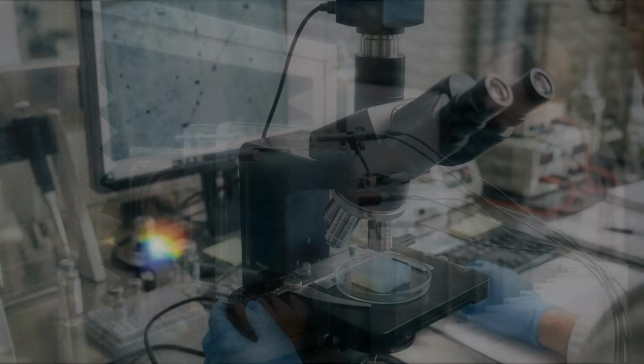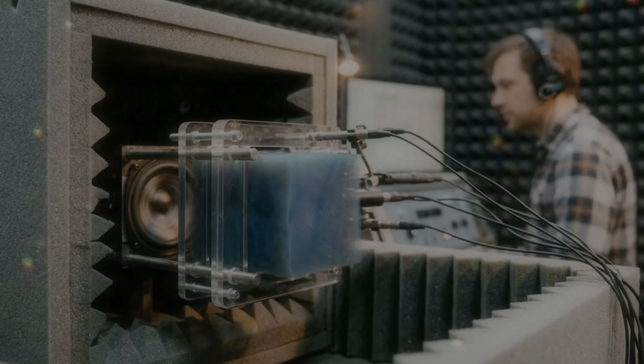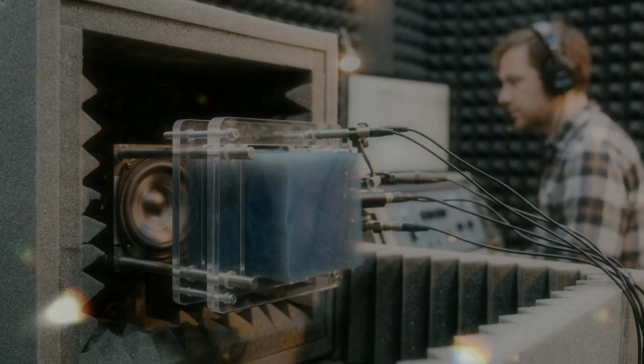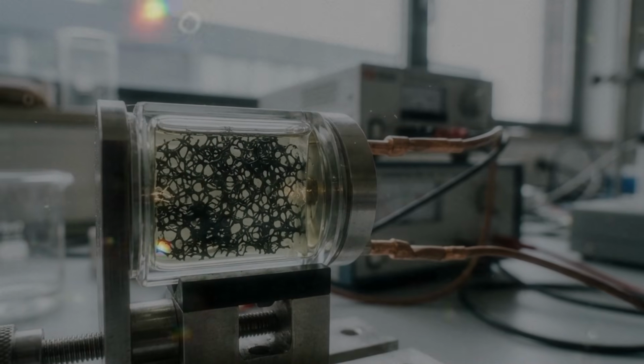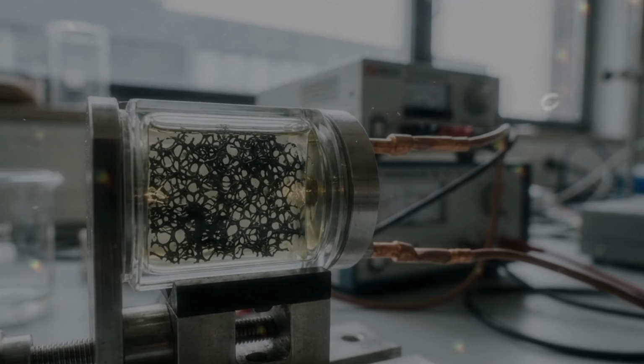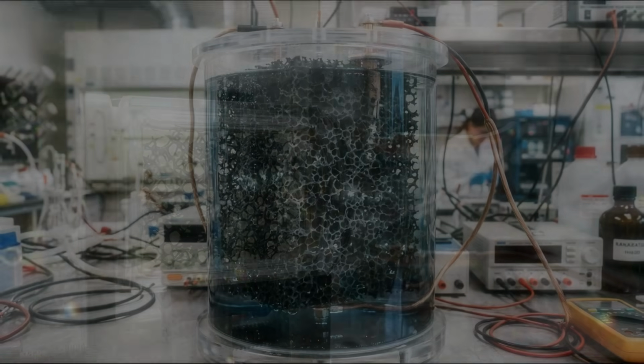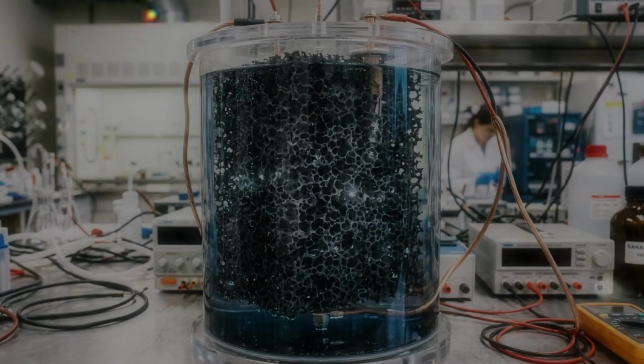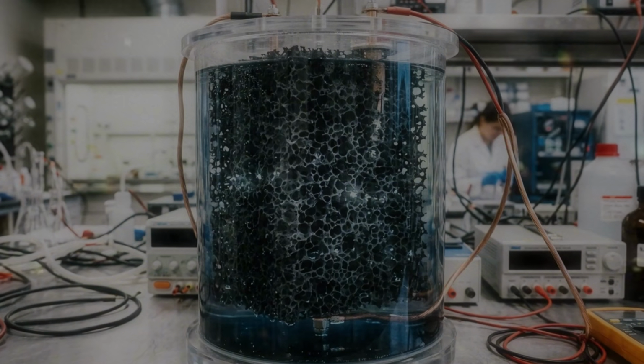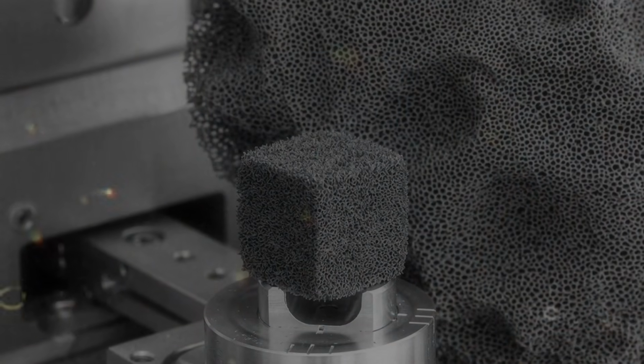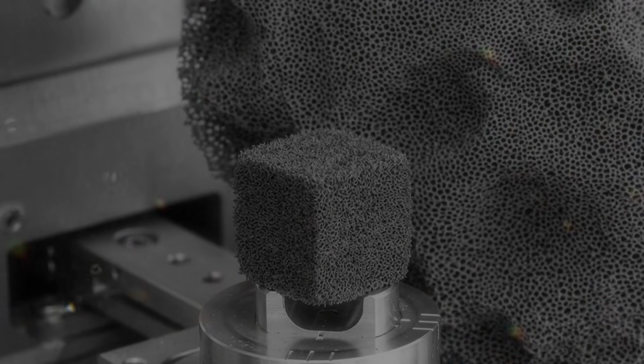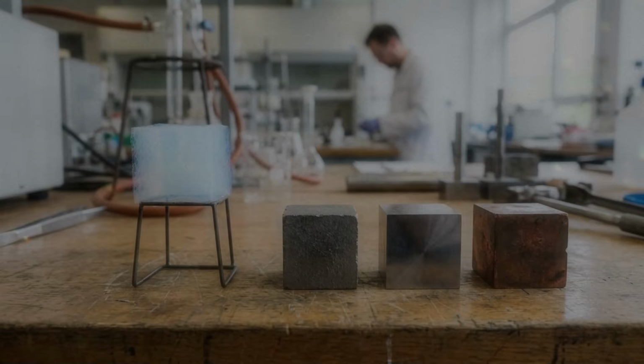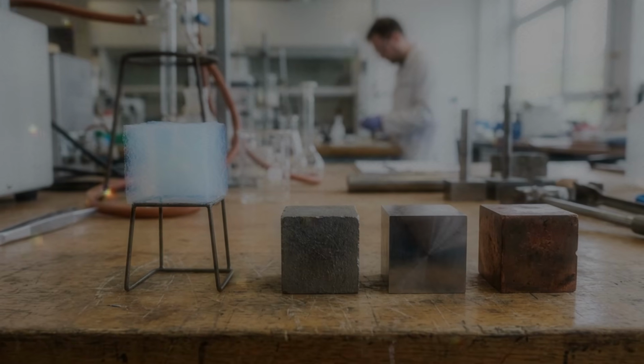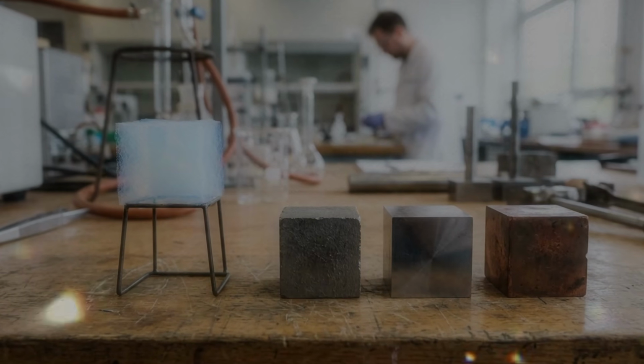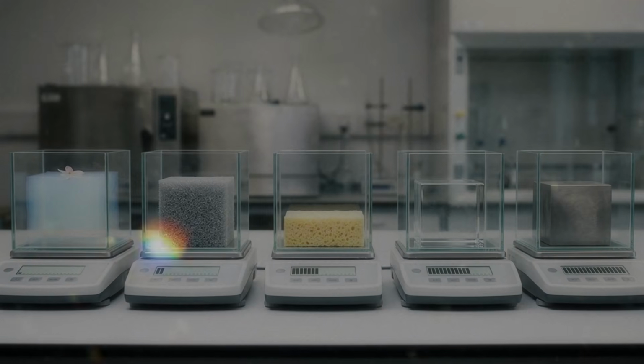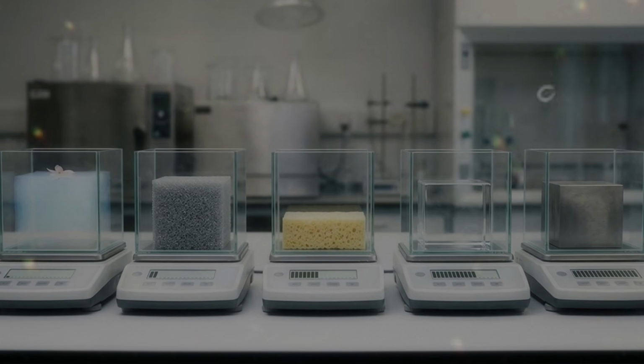A successful process does not need to preserve every pore perfectly. It needs to preserve enough of the structure to meet the intended use. Insulation for a wall may tolerate more shrinkage than a transparent optical panel. An oil absorbent may work well with large irregular pores. An electrode may benefit from a combination of pore sizes rather than one extremely delicate network. This change in thinking is important. The future is unlikely to be built from perfect aerogel blocks. It will be built from aerogels designed for particular jobs, with manufacturing methods chosen to provide the properties that matter and ignore the ones that do not.